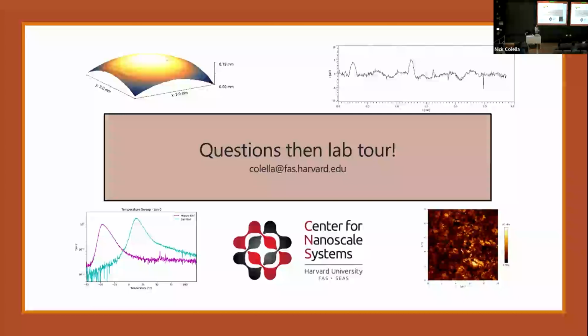Yeah. What dimensional resolution can you get for the FTIR? For this FTIR, you just place your sample on the crystal and we don't get any dimensional information. If you want to scan across a surface, we have at least two options. Raman microscopy gives a very similar type of data, looks at the vibrations of the bonds. So we can scan and map using Raman. That would be my first recommendation. We also have a reflection FTIR, which has a little bit lower lateral resolution, but you can also look around a surface, especially at a macro scale, to get data.